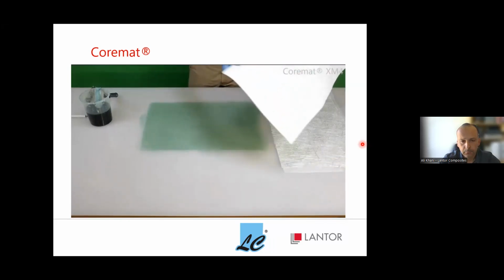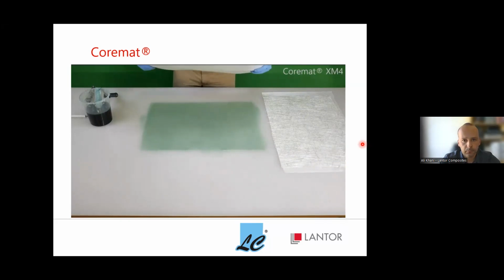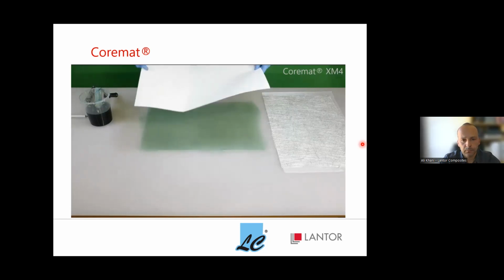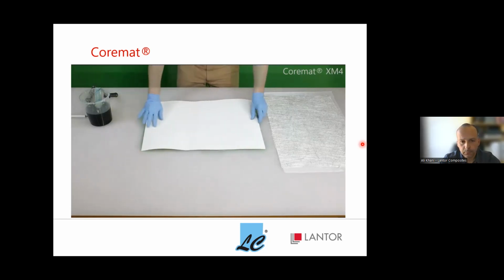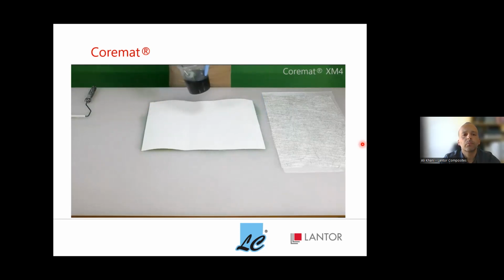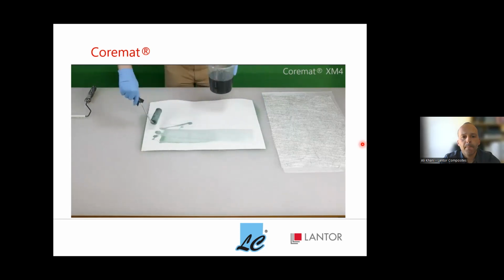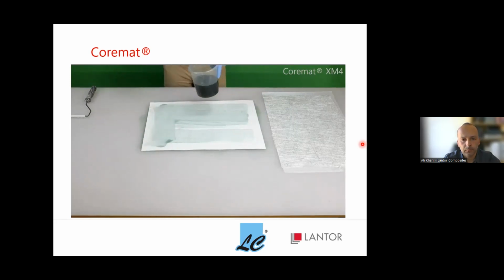Next up is the core mat. For this panel, we use the 4mm Coremat XM4. The 4mm thickness creates the stiffness in this panel that we need for the application. It is important for the panel strength to fully wet out the core mat. To make sure we fully wet out the core mat, we pre-wet the front side of the core mat, which is the smoothest side. We can roll the resin in the core mat without applying any force. We just have to make sure that the resin is spread over the surface of the core mat. To accomplish this, we use long motions, stretching the full length and the full width of the ply.